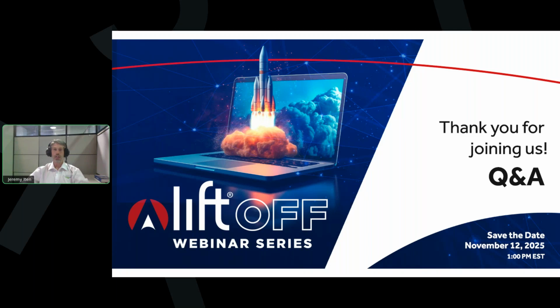A final consideration is that for things like titanium, less so for aluminum, but for titanium especially, you do need to control your oxygen level in that alloy. So exposure to moisture, exposure to oxygen over time can increase the oxygen level, and eventually you may get out of spec oxygen-wise for a titanium alloy. The oxygen will actually increase your strength, but it will also decrease your ductility, so you need to control your oxygen level. So that's something to consider with a reactive metal like titanium.